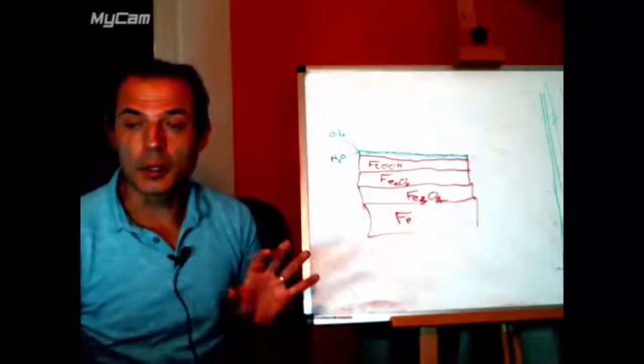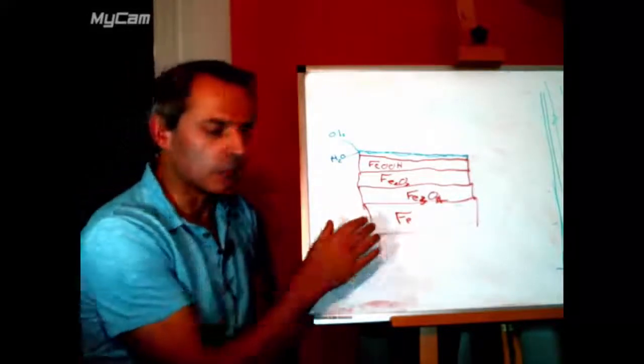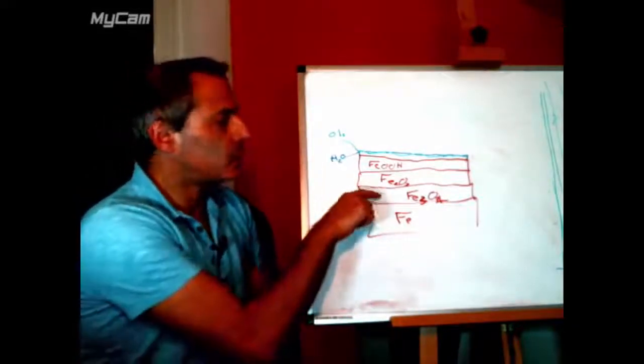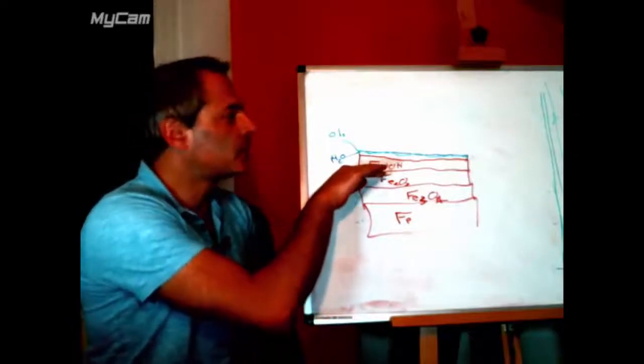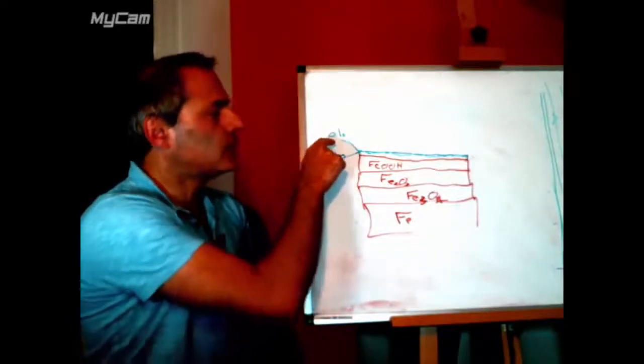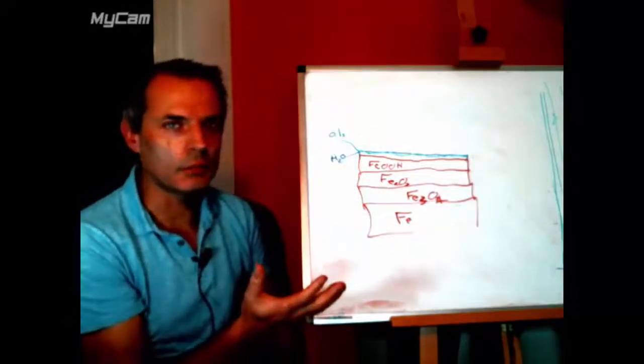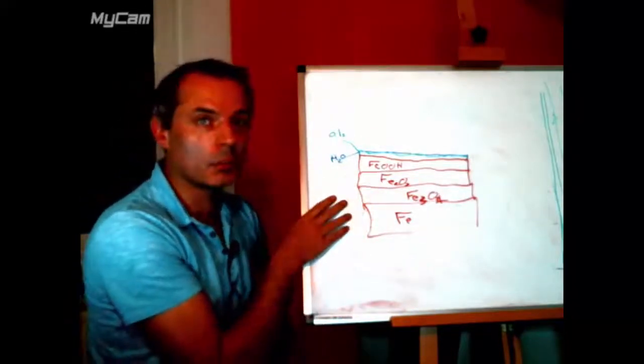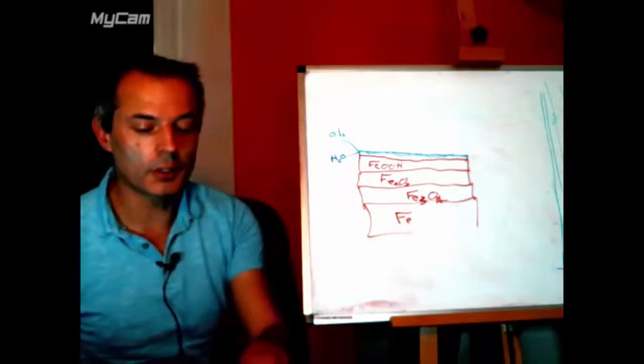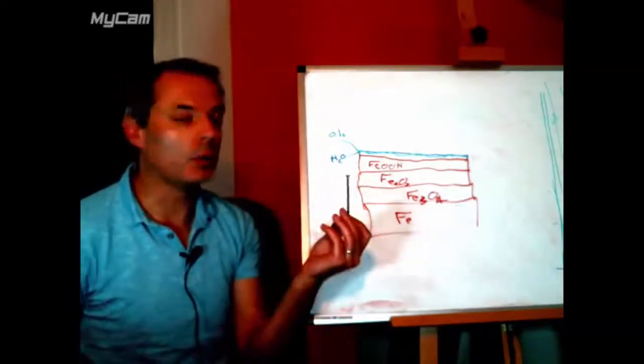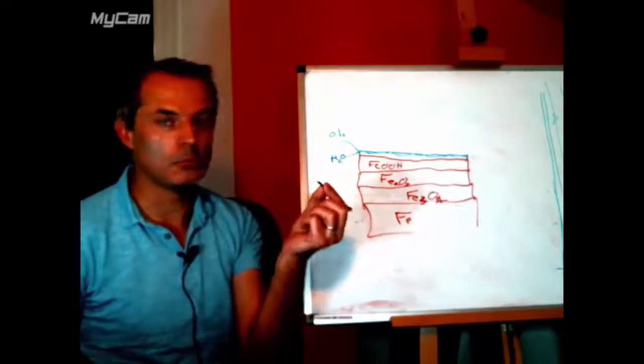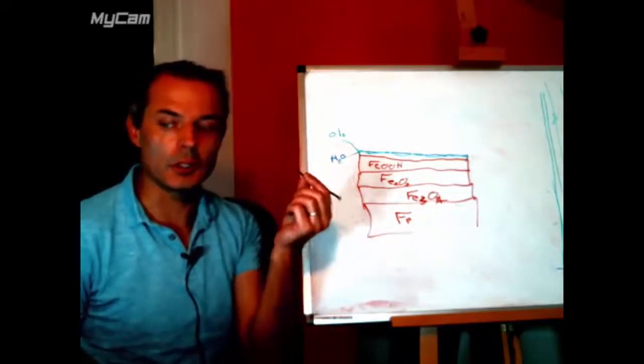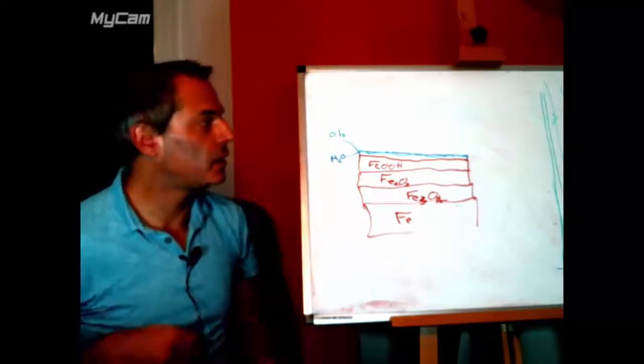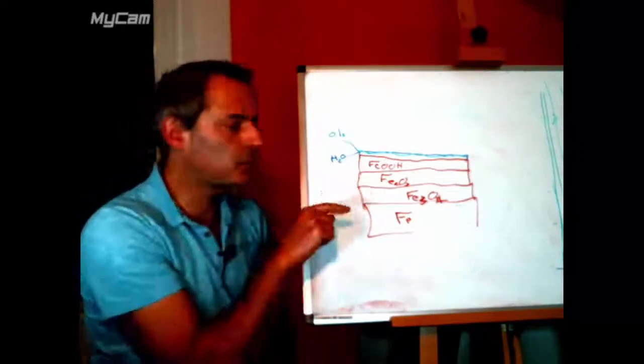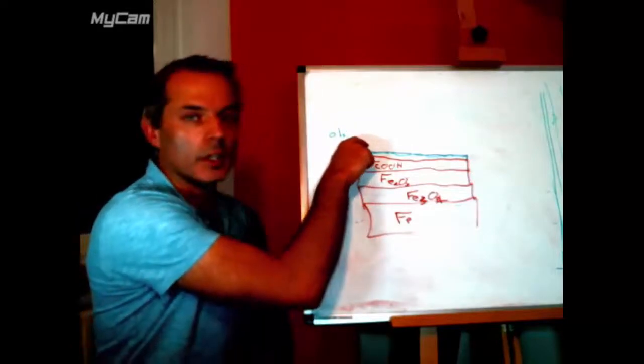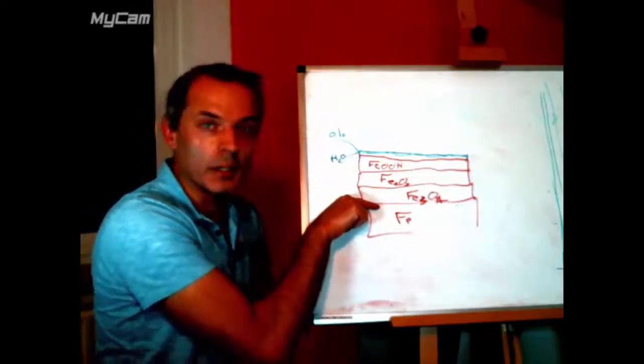And so to go back to our technical surface, here we've got our iron or steel. On the top of the iron we've got layers of oxides, and then on the very top of that we've got water and oils and all kinds of gunk that came from the atmosphere. So if we take this sample, for example, and we want to do something, paint it maybe, we want to deposit some zinc on it, electrodeposit zinc on it, then we have to bear in mind that we have all of this to get through first, because we don't want to put the zinc on the top of here. We want to put the zinc on the top of here.